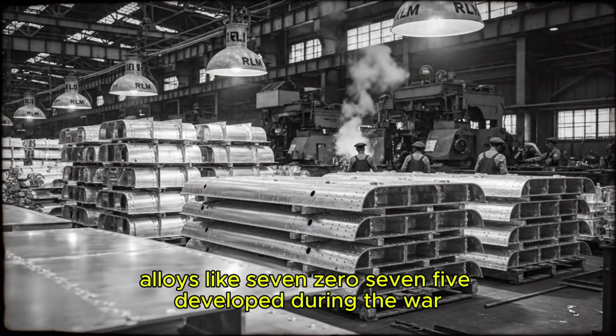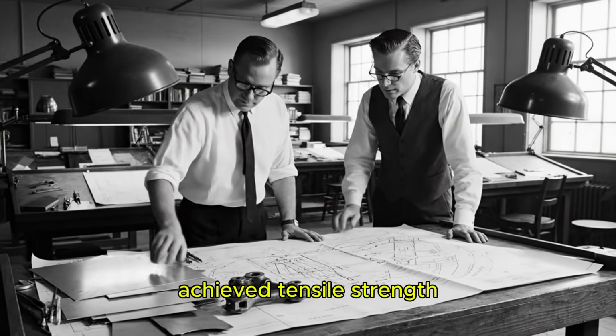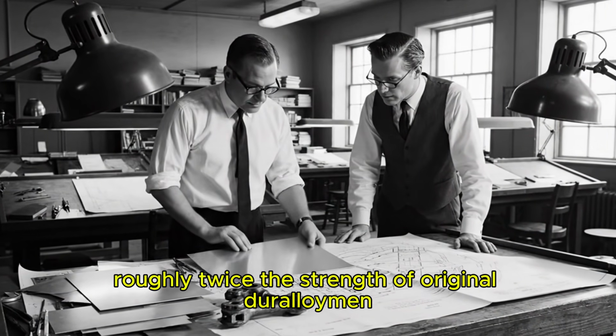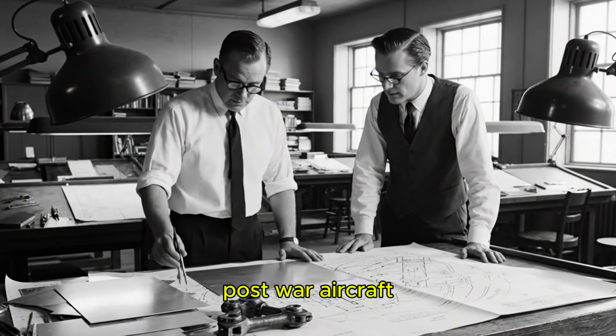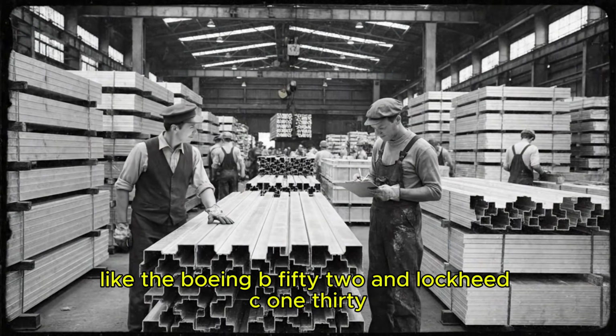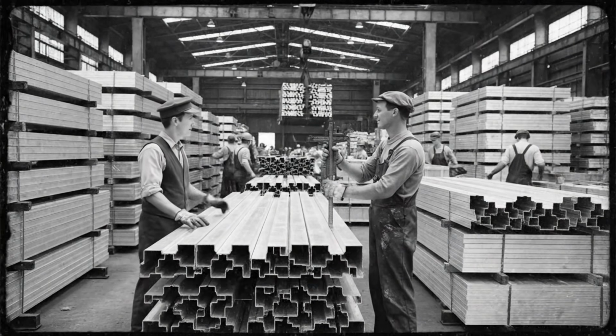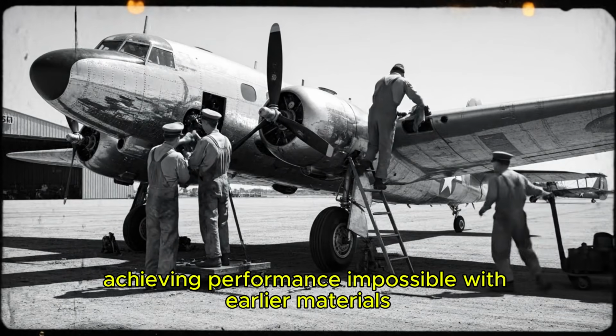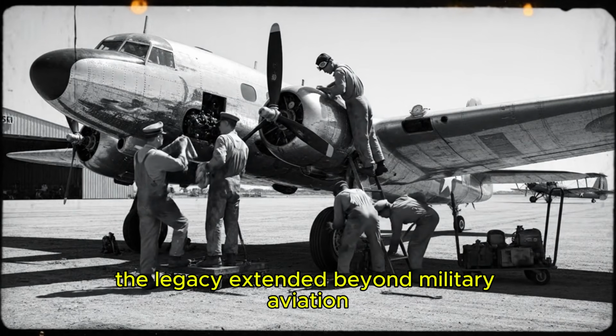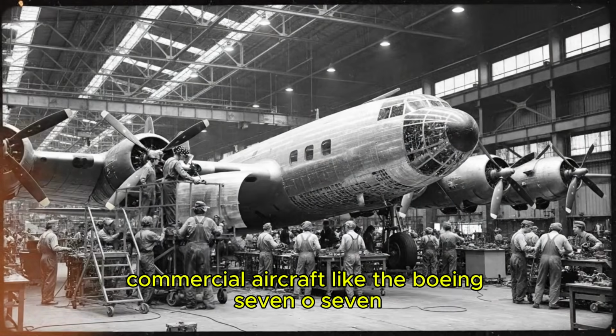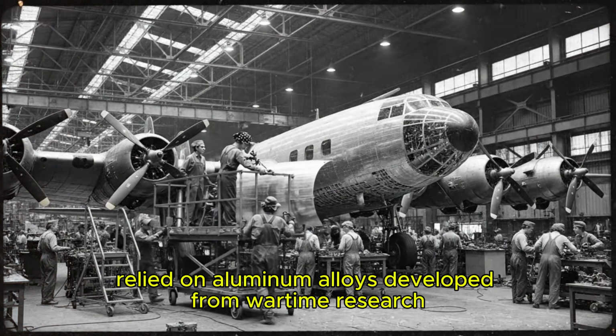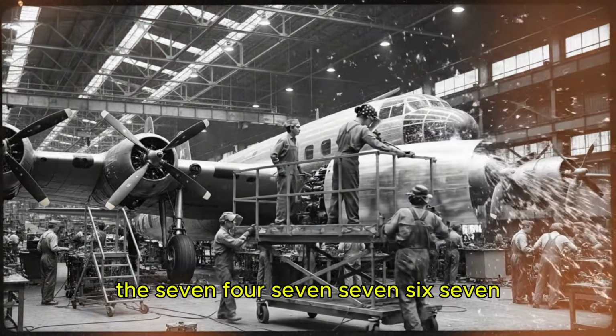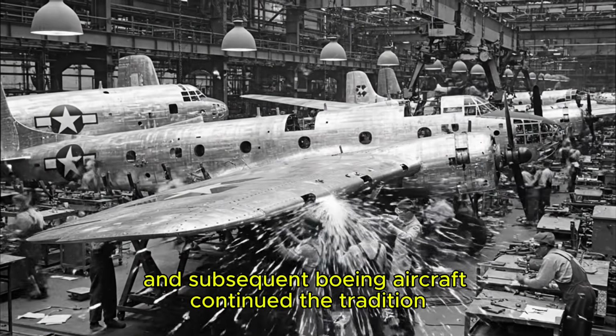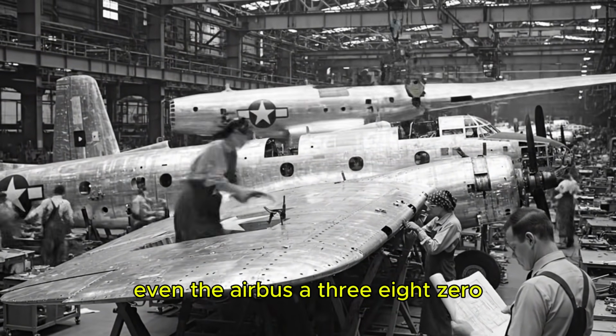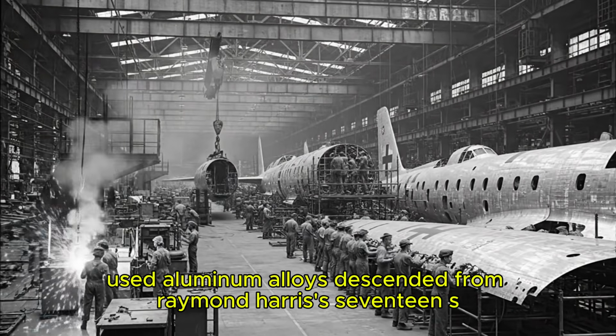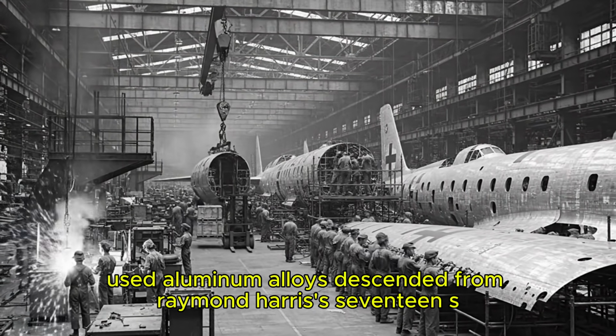Alloys like 7075, developed during the war, achieved tensile strengths exceeding 80,000 pounds per square inch, roughly twice the strength of original Duralumin. Post-war aircraft like the Boeing B-52 and Lockheed C-130 used these advanced alloys extensively, achieving performance impossible with earlier materials. The legacy extended beyond military aviation. Commercial aircraft like the Boeing 707, introduced in 1958, relied on aluminum alloys developed from wartime research. The 747, 767, and subsequent Boeing aircraft continued the tradition. Even the Airbus A380, first flown in 2005, used aluminum alloys descended from Raymond Harris's 17S.